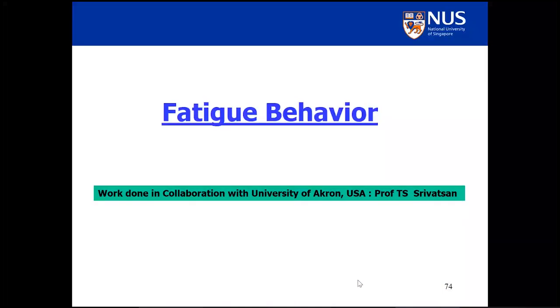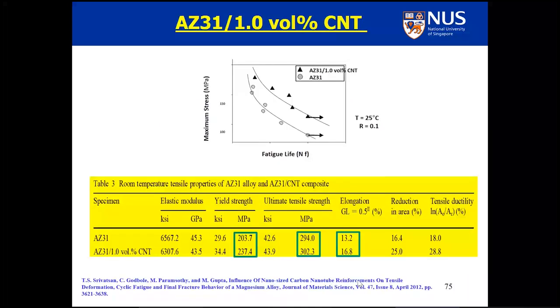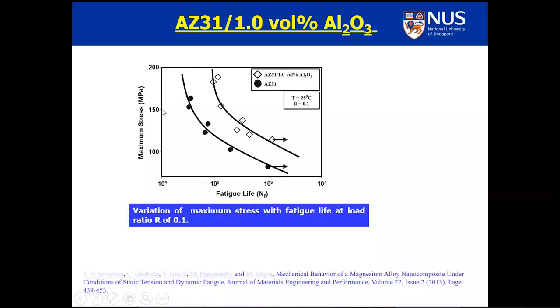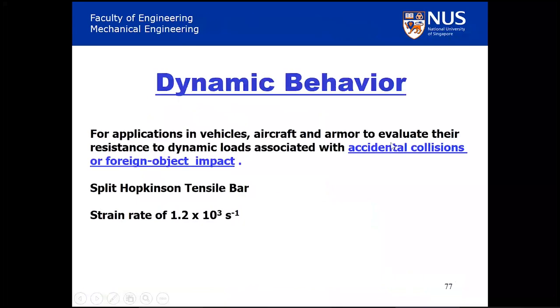So we also did some fatigue properties, the failure of material under cyclic loading. There I worked with Professor Srivatsan, who is an emeritus professor at the University of Akron. I gave him two sets of samples, commercial magnesium alloy AZ31 with CNT. Again, the strength goes up, and the ductility in this case also goes up. If you look at this S-N curve on the top, for a given stress level, the number of failure cycles is more for the composite material. Similar observations were made for AZ31 with Al2O3. Once again, for a given stress level, the number of cycles to failure for the composite is much higher. So not only under static loading, but also in cyclic loading, your properties are going up.